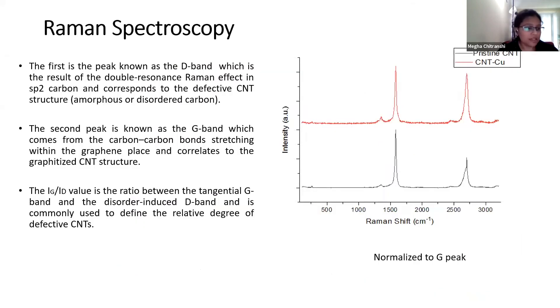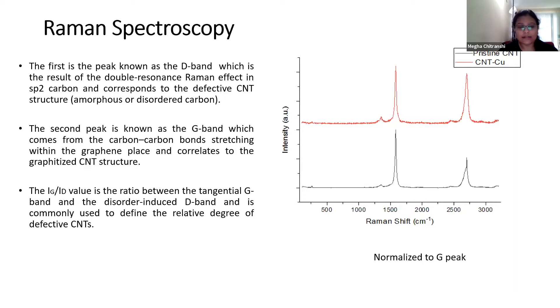This is Raman spectroscopy data. The double-resonance D-band around 1350 cm⁻¹ is induced by disorders such as crystal defects and amorphous carbon — the broad feature comes from amorphous carbon and the sharper features from defective CNTs. The G-band is associated with vibrations tangential to the tube surface. The intensity and width of the G and D-bands are characteristic indicators of quality and purity for the carbon sp2 structure; a smaller D-peak indicates fewer defects. It is expected that adding nanoparticles will cause the particles to bond with carbon nanotubes, converting sp2 bonds to sp3 bonds, so the G/D ratio is expected to decrease when nanoparticles are integrated.